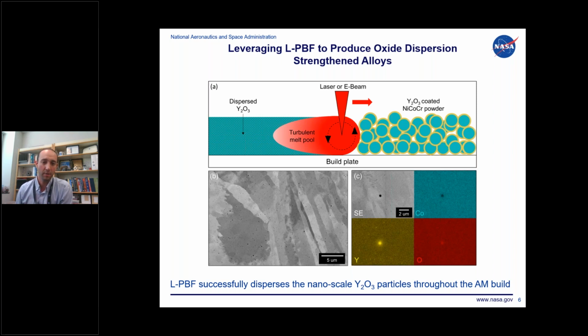The SEM image on the lower left here, you can hopefully pick up these really fine black dots in the micrograph there. Those are not pores or porosity, those are actually the nanoscale oxides evenly dispersed into your metal component there. You can see it doesn't really prefer grain boundaries or other locations. It really does appear to be evenly and randomly dispersed throughout the metal part.